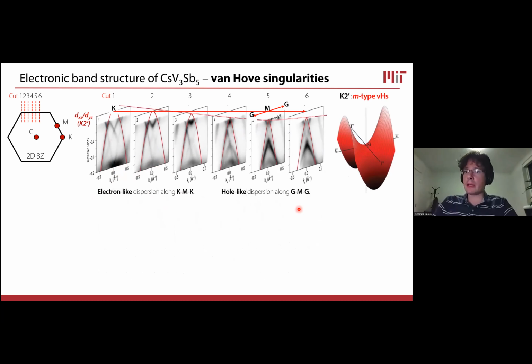And we see exactly the same behavior for both these bands. If we look at the other band, the K2 prime, which has the opposite type of Van Hove singularity, then we expect the same saddle point dispersion, just rotated by 90 degrees. So now we have a maximum coming back down from the K point, and then a minimum in this dispersion at M, and then the maximum of this sort of hole-like band that disperses back up towards the K point.